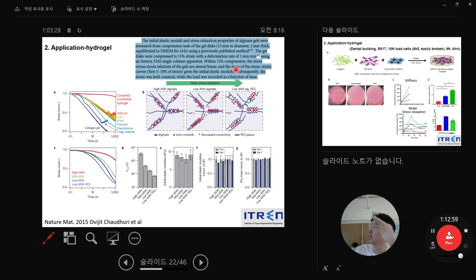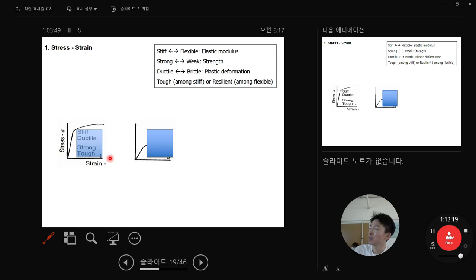And then the slope of the stress strain curve at 5 to 10% of strain is obtained for getting the elastic modulus. Subsequently, the strain was held constant, while the load was recorded as a function of time. So here, we can say that this is very linear, and from this linear part, when you measure the slope from here, or here, or here, you can have the same stiffness. But this is very theoretical. When we measure, we cannot take it like this. So in that case, you have to determine which slope you use to obtain the initial stiffness. Here, here, or here. That is why they mention it like this.